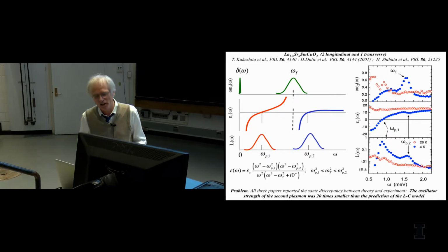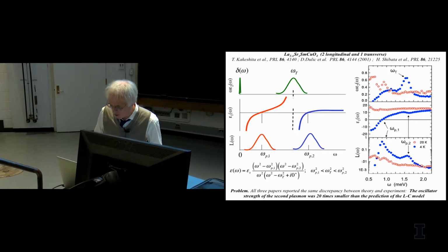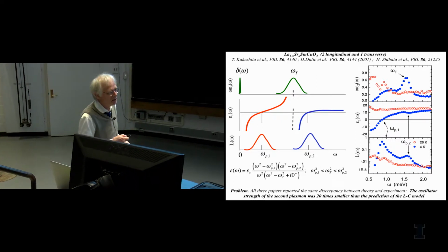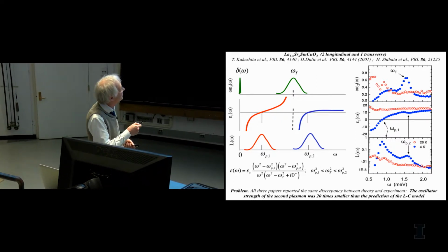In fact, this was, let's say, also by intervention of the editors of PRL, that they actually put 3 experimental papers independently confirming this picture, of which I show one, which was from our own group, showing that indeed there is this peak over here in the superconducting state. The red curve is in the normal state. There's a peak over here. There's a zero crossing here.